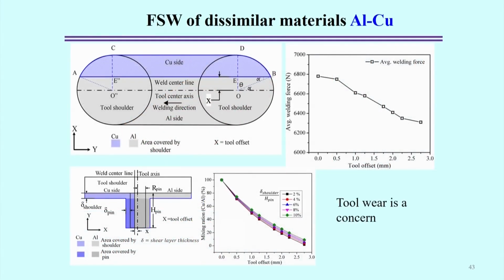Now, in the further analysis of FSW of dissimilar materials, this figure shows the highlighted part. That means if we put the tool offset towards the copper side, then the mixing volume ratio during the stirring and rolling process between copper and aluminum is a function of the tool offset. If we increase the tool offset, the volume of the aluminum generally increases, and at the same time there is a reduction of the volume of copper in the mixture. So that is controlled by the amount of the tool offset.